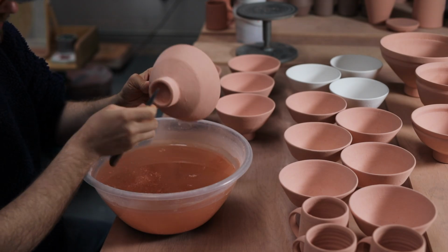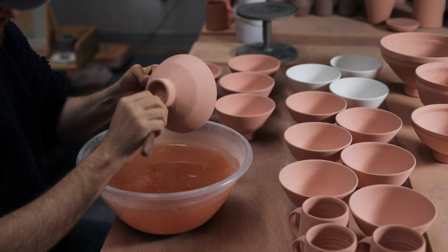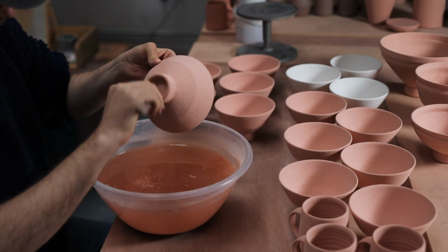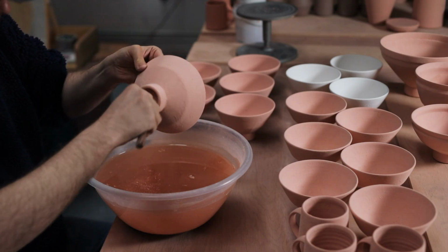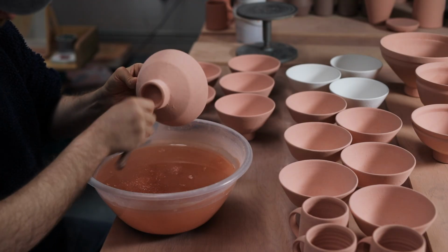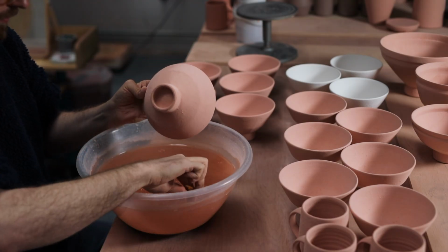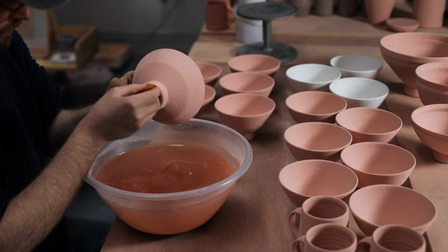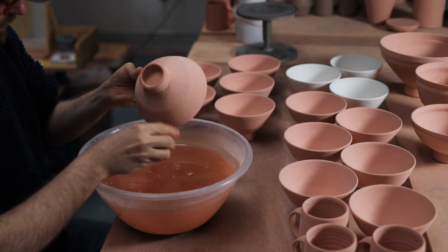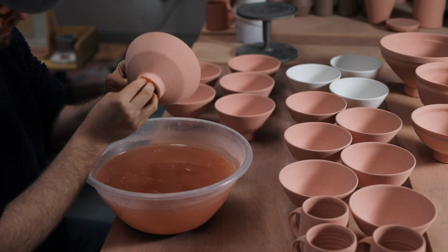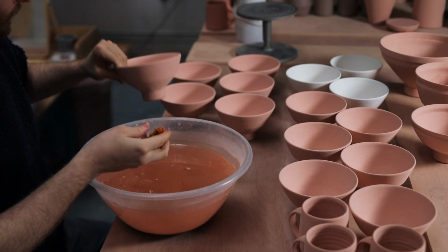I use a small knife to carve around the foot, scraping away any droplets that have held onto the waxy surface, and then I use a small sponge which I soak in water and carefully fettle all the way around the edge, both inside and out. It's this that gives me the really crisp finish.